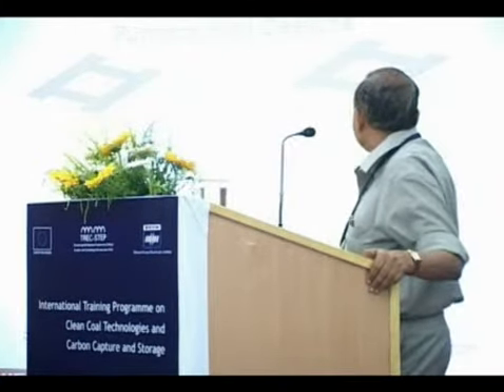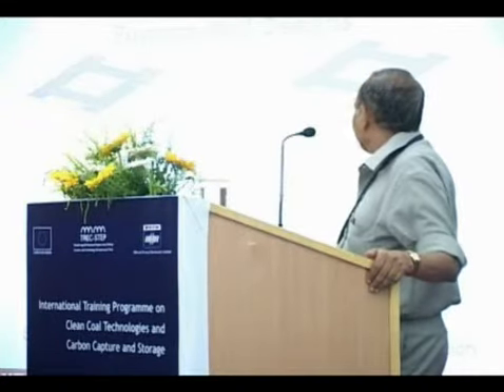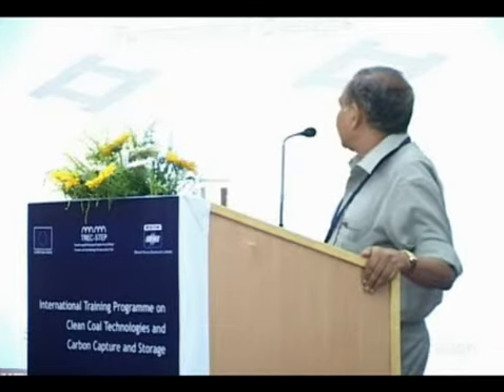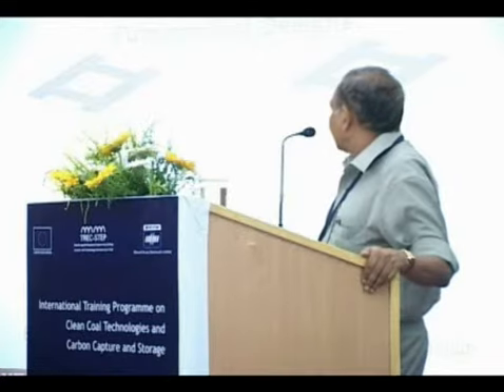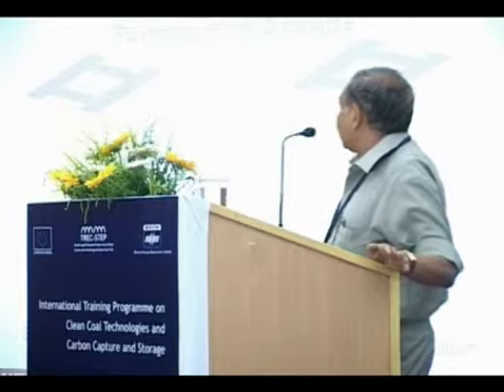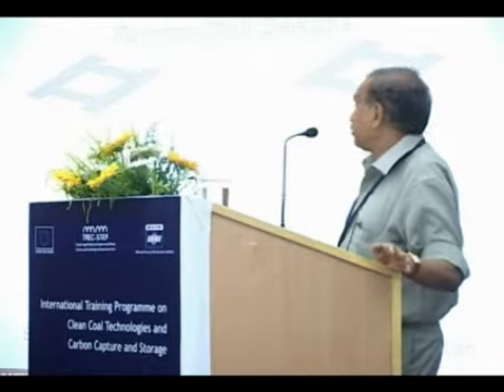Now you see, in these boilers, in order to protect the water wall tubing, we go for what is called spiraling in the furnace. Now in these boilers you can see the lower portion of the combustion chamber, unlike the subcritical boilers where we use a straight tube, we go for spiraling of the tube. This is to ensure that we provide adequate cooling when you operate from 40% load to 100% load. Below 40% load, we will go for circulation. Above 40% load, the tube has still to be protected. So, we go for very low diameter tubes like 38 mm tube compared to 51 mm tube or 63 mm tube in the circulation boilers. So, this lower diameter tube coupled with the spiraling will ensure that protection of the furnace is ensured.